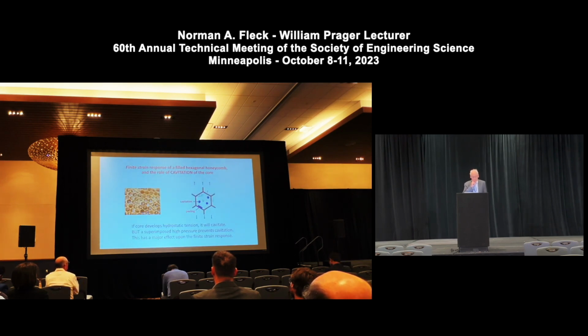In practice, when we do the experiments, there's an added bit of physics which can come in. And the added bit of physics is non-trivial. It's the fact that cavitation of the core of this honeycomb can take place. And you can think about it in two ways. You can say if the honeycomb wants to inflate, or wants to dilate, I should say, with tension in the liquid, then bubbles could form, cavities can form, and the core could actually increase in volume, or peeling could take place between the core and the wall.